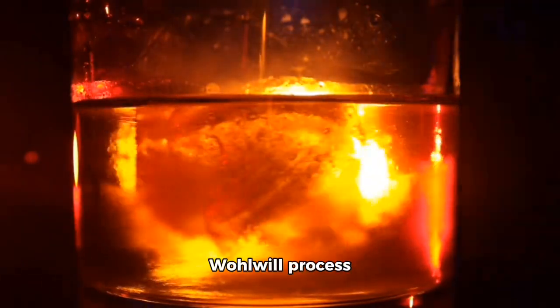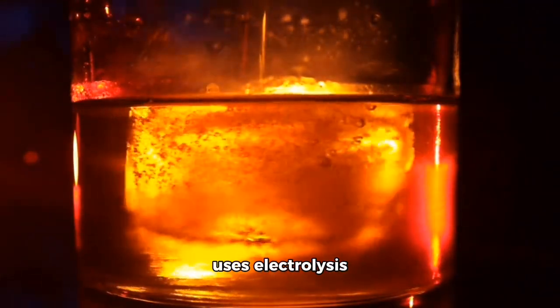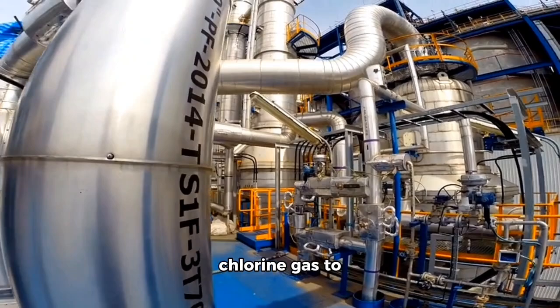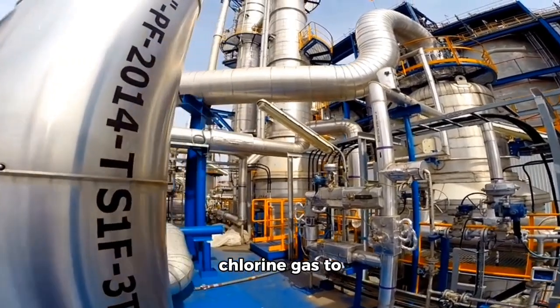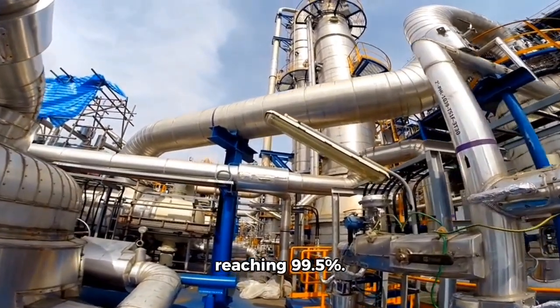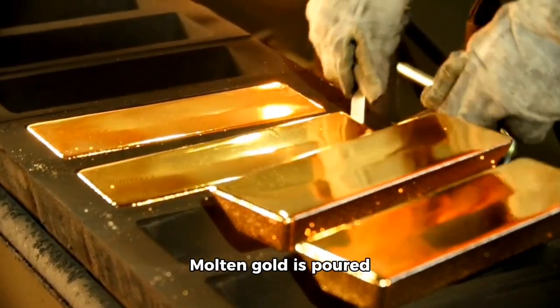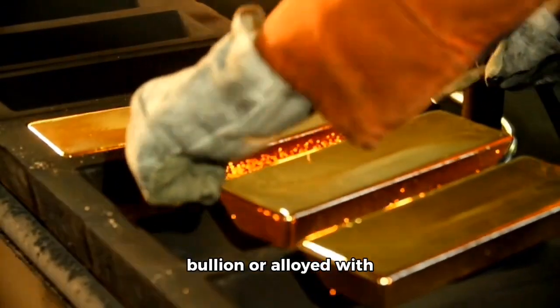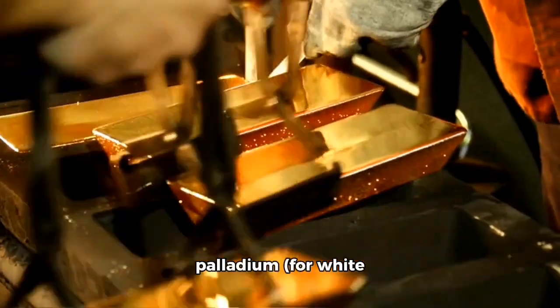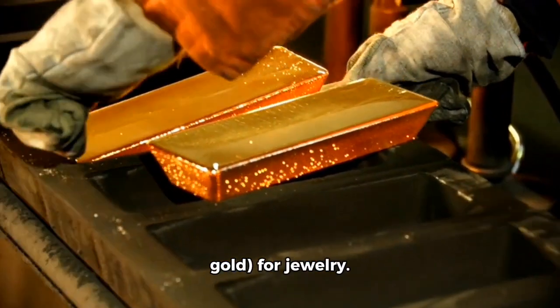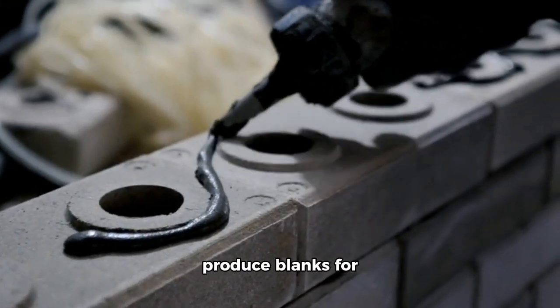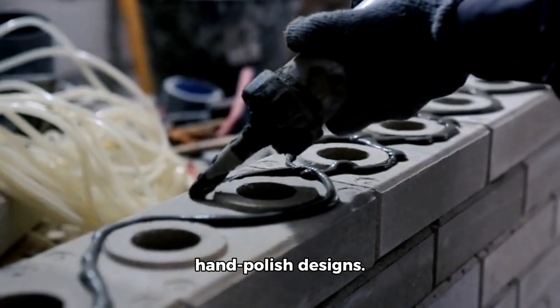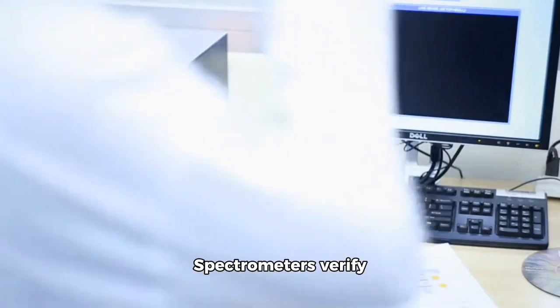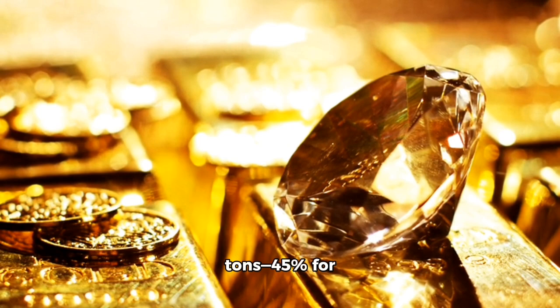Refining via the Wohlwill process uses electrolysis in a gold chloride bath, achieving 99.99% purity. The Miller process, faster, injects chlorine gas to remove base metals, reaching 99.5%. Molten gold is poured into 400-ounce bars for bullion or alloyed with copper for rose gold or palladium for white gold for jewelry. Casting machines produce blanks for rings, while artisans hand-polish designs. Spectrometers verify purity, and X-ray scanners detect flaws.